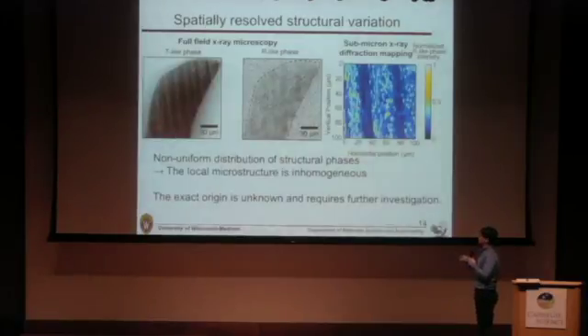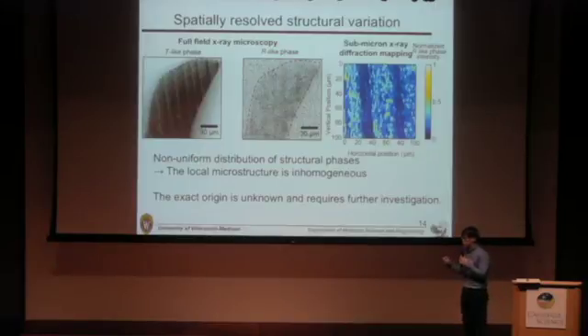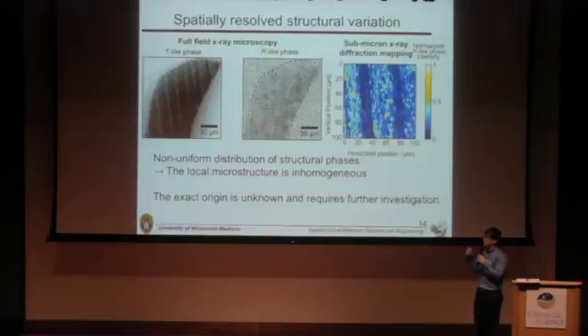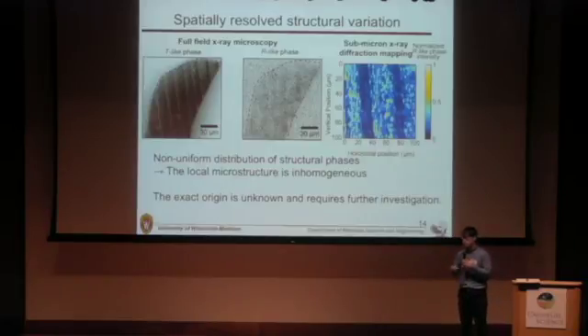And we did the full field X-ray microscope and also sub-micron X-ray diffraction mapping to study the microstructure of the system and see these stripe patterns in the T-like phase and the inhomogeneous intensity distribution in the R-like phase. But we think that this means that the local microstructure will be different and also the local strain state. But because of the limited resolution of the X-ray, we cannot exactly resolve the origin of these different structures, different degrees of the structural transformations.